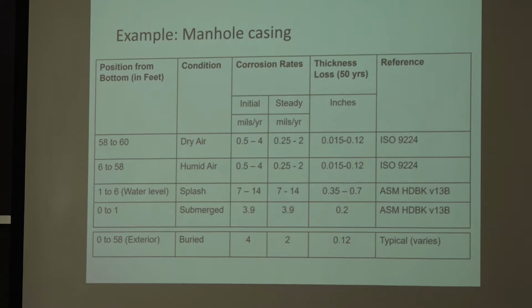Is the scale, what's the scale made of? Is it oxide or micro...? Hydroxides and oxides, and there's a very complex chemistry there. And then natural, like organic life as well? No, it's typically inorganic. I showed a sample earlier. You have magnetite in there. You have different layers depending on the pH you're at and how dry or wet the environment is.